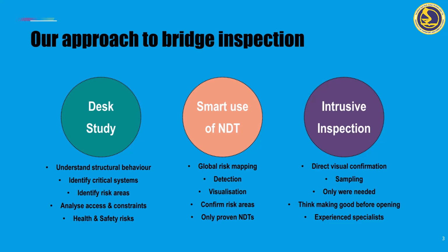So either in order to get direct visual confirmation of some damage to the structure, we can do material sampling, for example, if we don't know the concrete strength or the steel characteristics. But this is really something we should limit to those areas where it's really needed. And we need to think from the start, how do we make these areas good again? Because if you take, for example, a concrete sample in a bridge deck, which is otherwise in good condition, you might create an area of weakness where maybe you get water in, and then you can cause corrosion over time. So it needs to be well planned. And I think this is also where it's very important that experienced specialists are tasked with doing these works.